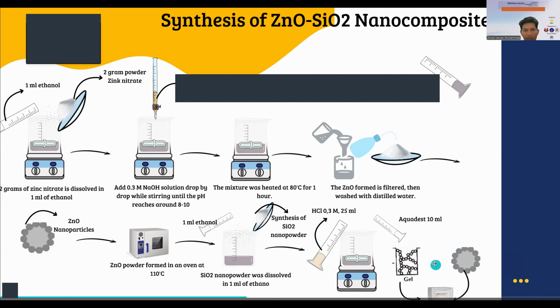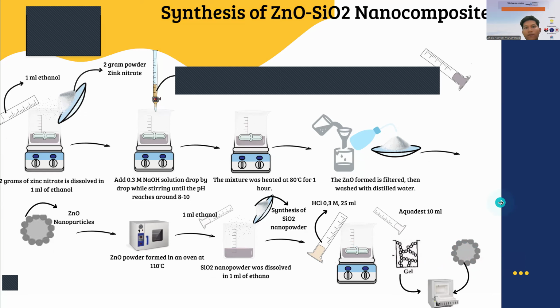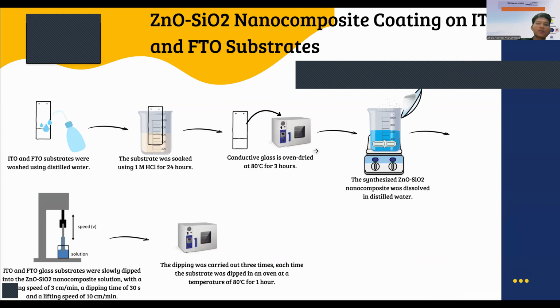The ZnO-SiO2 powder was calcined at 800 degrees for 2 hours. Next step is ZnO-SiO2 nanocomposite coating on ITO and FTO substrate. The ITO and FTO conductive glass substrates were cleaned with deionized water, followed by ethanol before use.